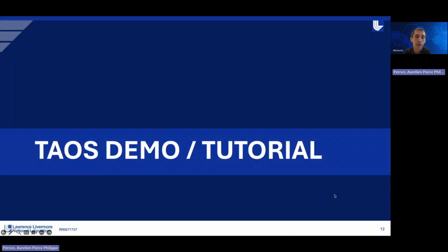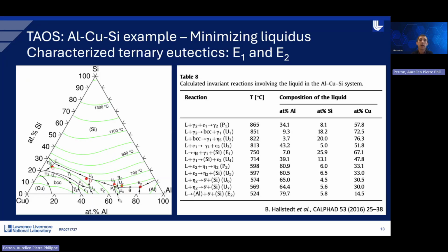So now coming back to some examples of how you can use the software. Here I will talk a little bit about the aluminum-copper-silicon system. This is an example that you can find in the TAOS documentation. You don't have to be really familiar with, for instance, this liquidus projection in the ternary system, but it's just to highlight what the software can do for you. Here, for instance, if you're interested in minimizing the liquidus of your system, that's the temperature at which your alloy, if you start from a high temperature where it is completely melted, and you decrease the temperature, would start to solidify.